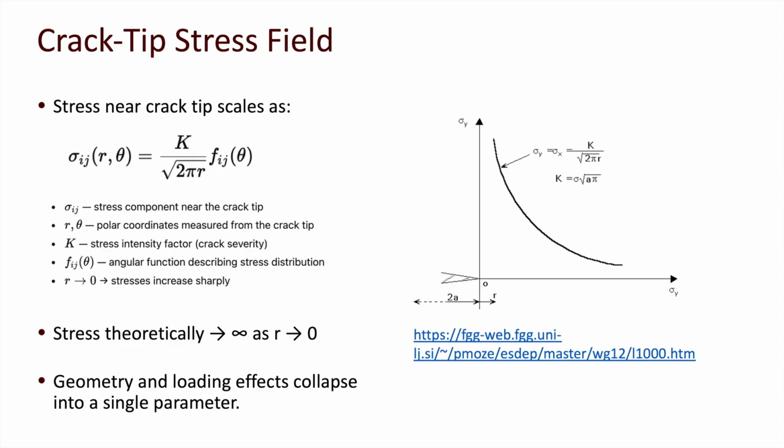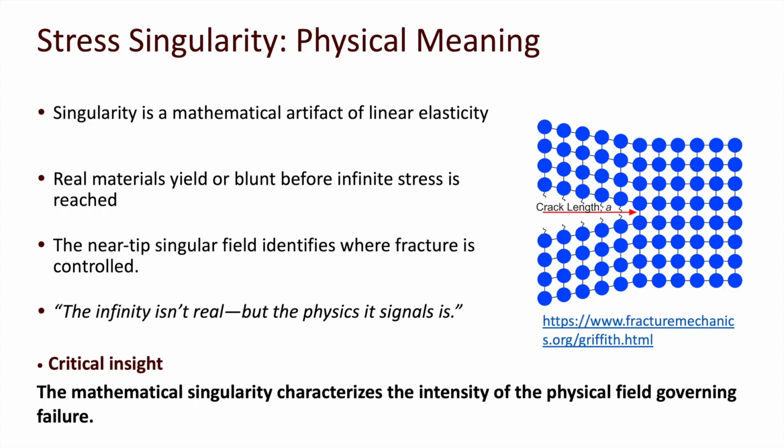A key implication of this solution is that, mathematically, the stress approaches infinity as the distance to the crack tip approaches zero. At first glance, the stress singularity predicted by LEFM may seem unphysical. After all, real materials cannot sustain infinite stress. In reality, materials yield, blunt, or otherwise deform near the crack tip before any true infinity is reached. The singularity is therefore a mathematical artifact of linear elasticity.